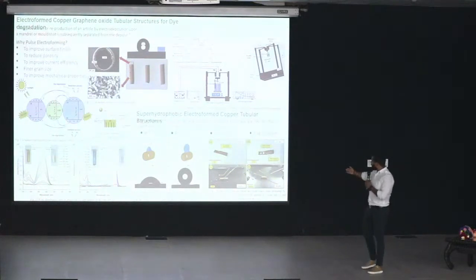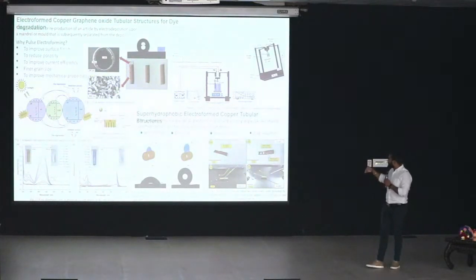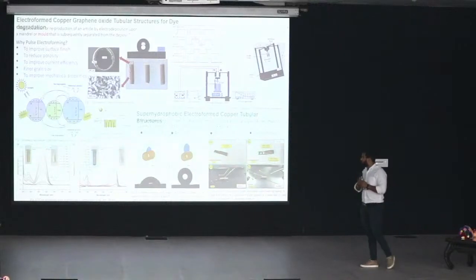And the other image is showing that when a water jet impinges on the surface, it spreads out throughout the surface in the case of superhydrophilic. And in the other case, when the tube is superhydrophobic in nature, the water jet impinges and is reflected back in the same direction.